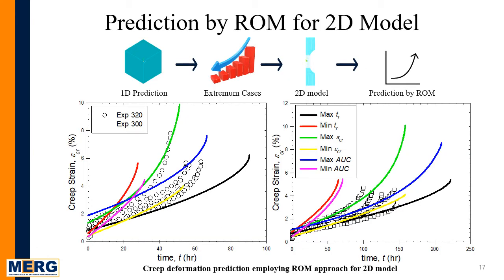So at this point, we are employing the reduced order modeling approach. We take the extremum cases from the probabilistic prediction from the 1D model, and those extremum cases are retrieved for the 2D model, and the prediction is done by the reduced order modeling approach. Those numerous probabilistic predictions are reduced to just 6 plots, but we are still retrieving the scatter bands that are established by the 1D predictions.